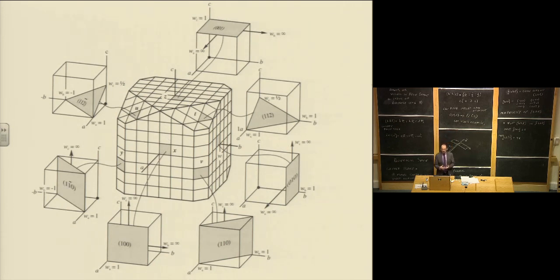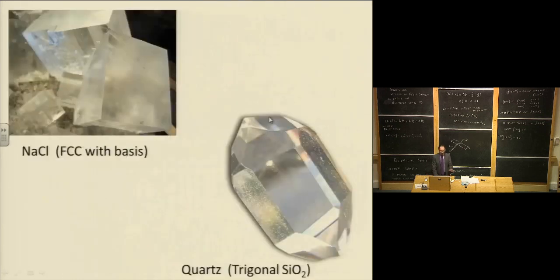It's not a hard and fast law, but it's a very, very good rule of thumb by Bravais, known as Bravais' law, the same guy who worked out all the lattices. And it actually tells you that when you take a cubic crystal and you break it, you get only the 1, 0, 0 faces. Occasionally you'll get the 1, 1, 0 faces, and even less occasionally 1, 1, 2. So here's a picture of sodium chloride, which is a cubic crystal. It's actually an FCC crystal, and it breaks almost exclusively along the 1, 0, 0 lattice planes. You can see that these breaks are entirely at 90 degrees.